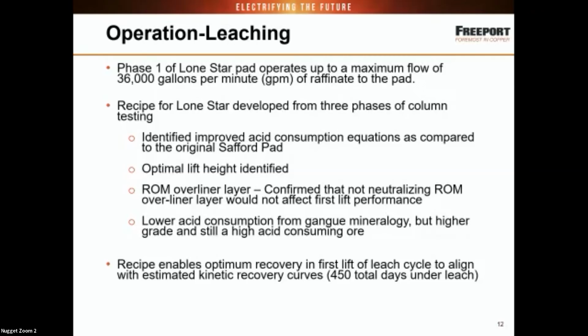This time, obviously, lower acid consumption from gangue mineralogy, but we have a high grade, so it's still a high acid consuming ore. There's virtually no calcite in Lone Star ore. We hardly ever see more than a fraction of a percent. So the recipe enables optimum recovery in our first leach cycle, and it aligns with our kinetic recovery curves, which is a total of 450 days.